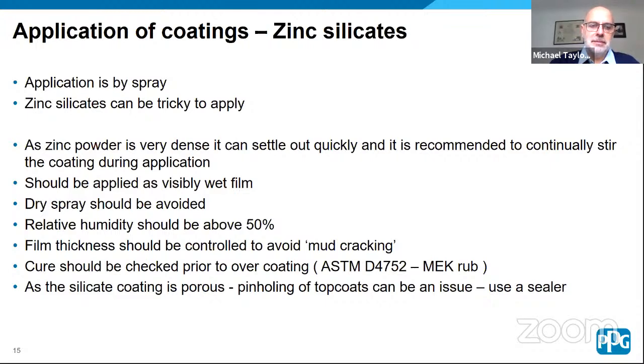Zinc silicates do require some moisture cure, so the relative humidity should be above 50%. If you try to cure them below 50% humidity, it takes an exceptionally long time. In fact, zinc silicates are one of the only coatings where I can advise you, if you're finding the cure is a bit slow, to actually pour some water on top of it. It won't affect the coating once it's dried, but it will accelerate the cure.